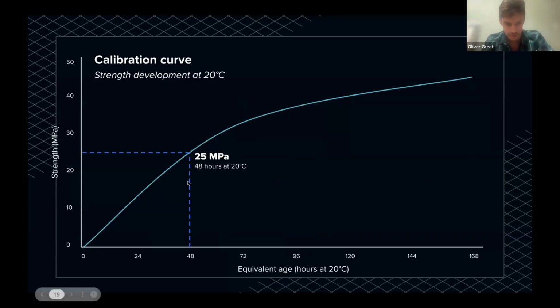So I'll run through a quick example here just to illustrate exactly how it's working. So we've established our calibration curve here. This was done using cubes cured at 20 degrees Celsius in standard conditions. A number of crushes have been taken and this curve is generated. Now the contractor in this case is looking to perform something like post-tensioning, and they're looking to obtain that key strength of 25 megapascals, which in the calibration was observed at 48 hours from the cube samples.